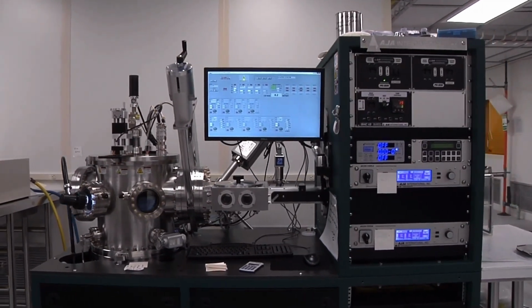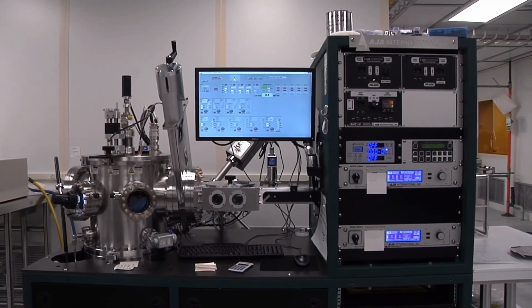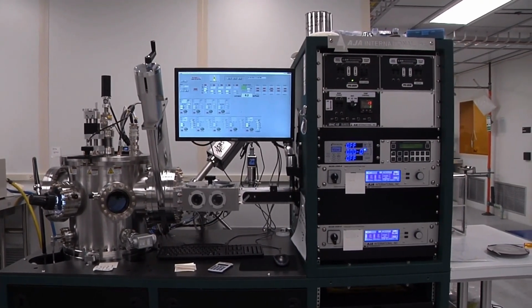That's what that machine looks like. And we used that to work out the parameters. And what we did was we figured out a set of parameters that we could use during sputter deposition to make thick films that were fairly stress-free.